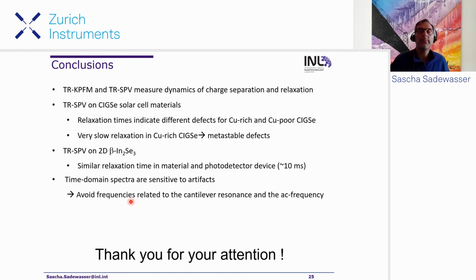So finally, to conclude, I showed a couple of examples to measure charge dynamics by using time-resolved KPFM or time-resolved surface photovoltage. In the CIGS samples, we saw differences in the defects between copper rich and copper poor. In the 2D materials, we confirmed that the time dependence of the photodetector devices is actually due to the material. And finally, the time domain spectra can be sensitive to artifacts, and it's best to avoid frequencies in your spectrum, when you design your spectrum, that are related to the cantilever resonances and also to the AC frequencies.